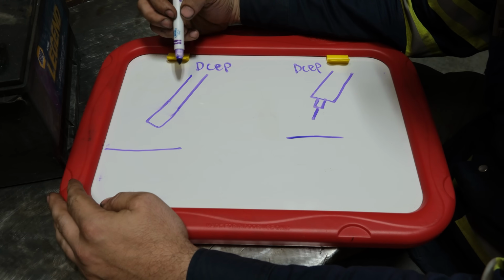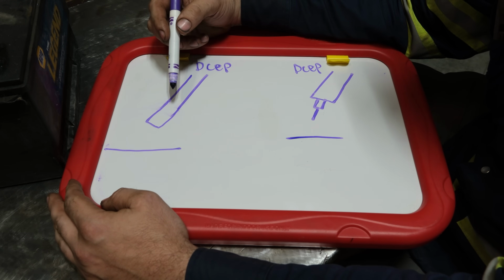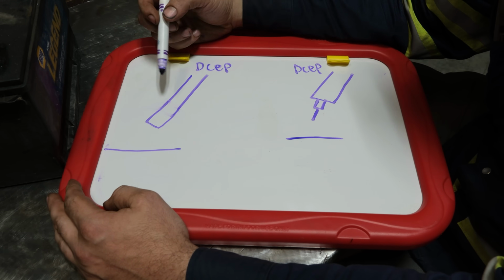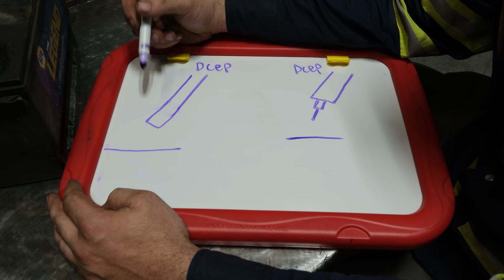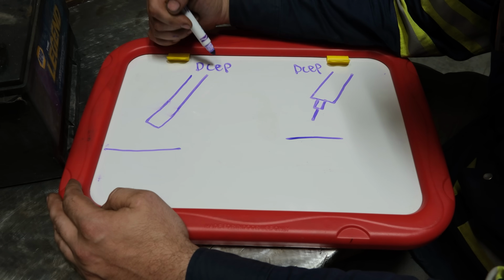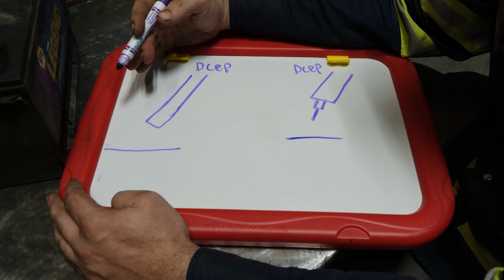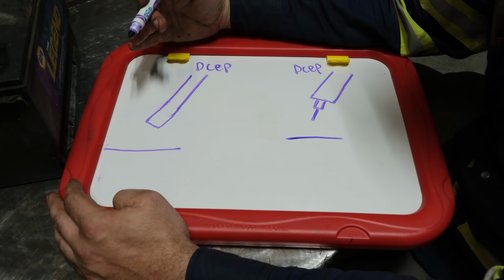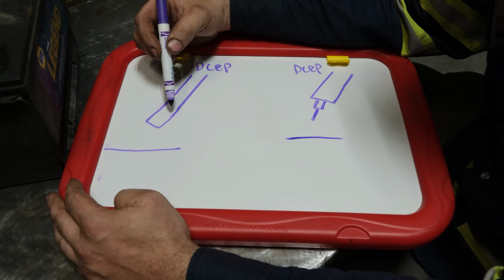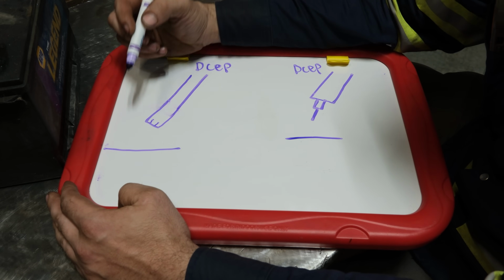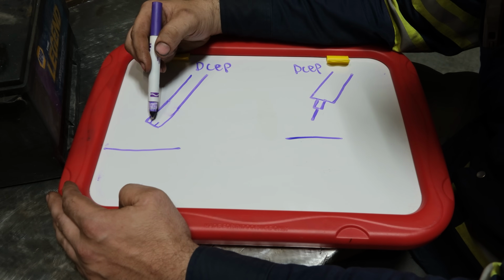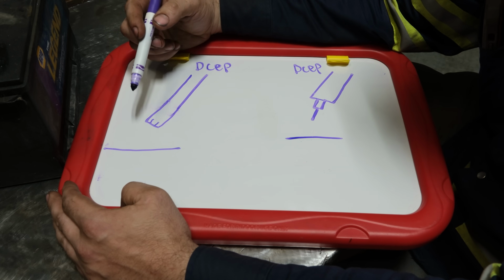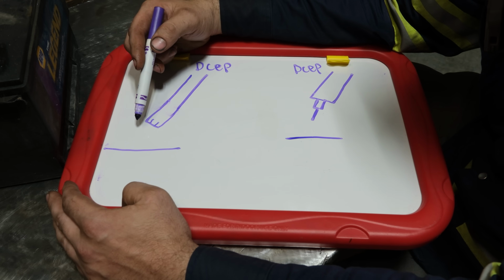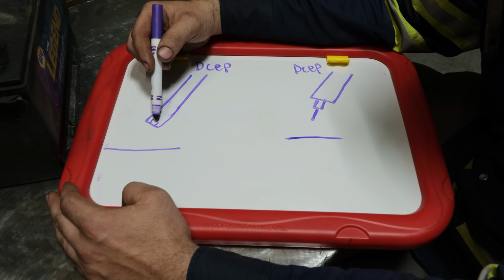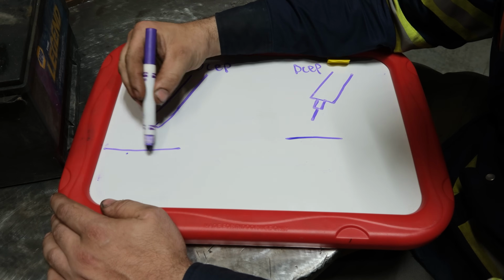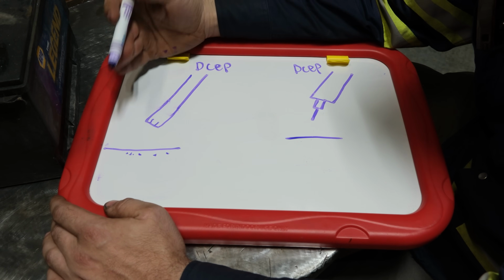So stick welding operates on DCEP, electrode positive, just like your typical gas shielded MIG also runs DCEP. Now, in the case of TIG, like I mentioned, if you ran EP, you would consume your tungsten and it would melt because it can't handle the heat and it's not meant to be consumed. Well, with stick welding, where you have an inner wire core, electrode positive doesn't matter because that wire rod is consumed anyways as part of the welding process. So the fact that you're inputting massive amounts of heat due to the impacting of the electrons from your plate to the tip doesn't matter.